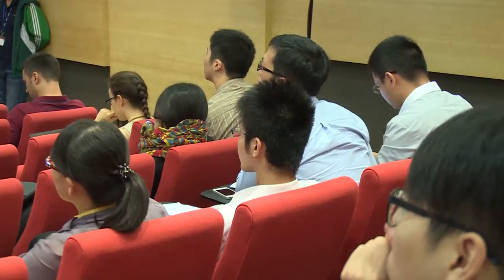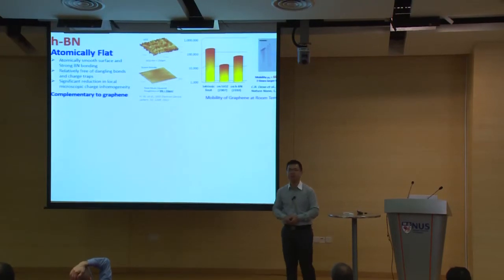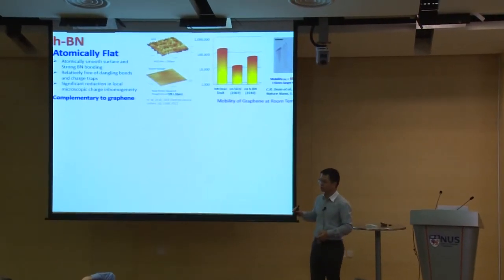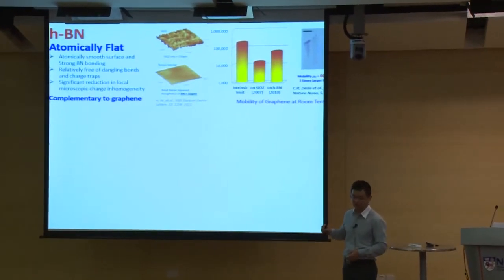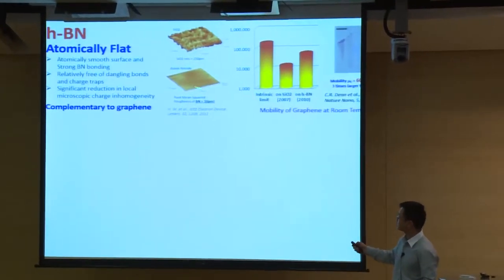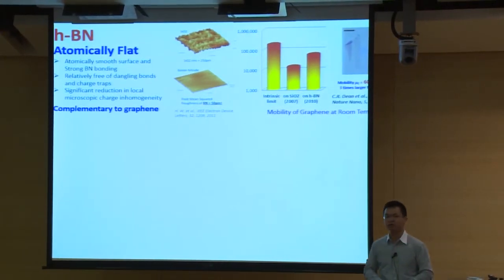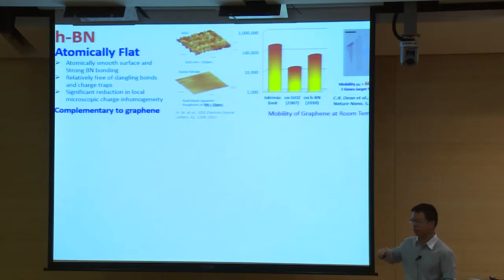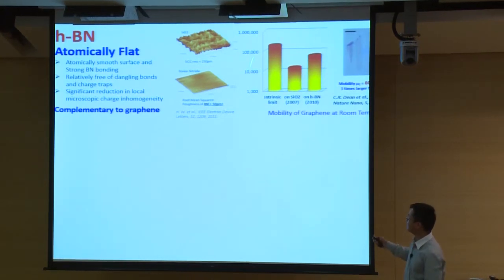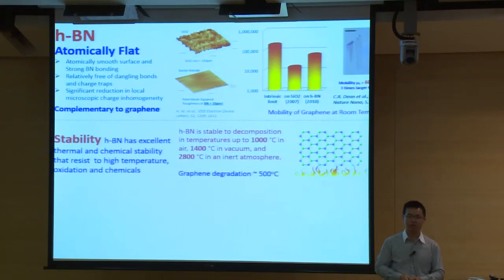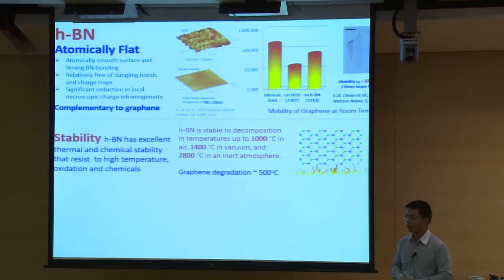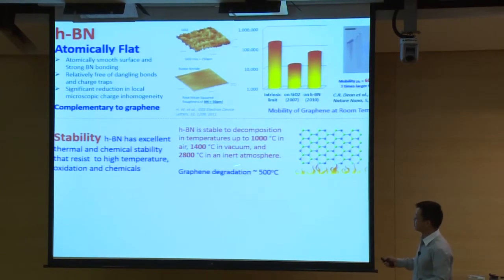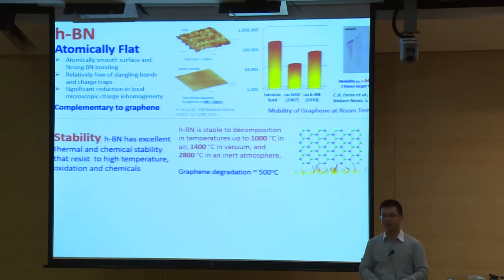So for the boron nitride, first of all, boron nitride is a very flat material, as you already know. So the average roughness of boron nitride is only 1/5 of that of silicon oxide. So if we can put graphene on boron nitride, the mobility can be significantly increased to close to the intrinsic limit. And also boron nitride is a very stable material that can resist high temperature and also chemicals. So if you oxidize boron nitride at 1,000 degrees, it can still survive. But as a comparison, graphene will degrade at a temperature of 500 degrees.